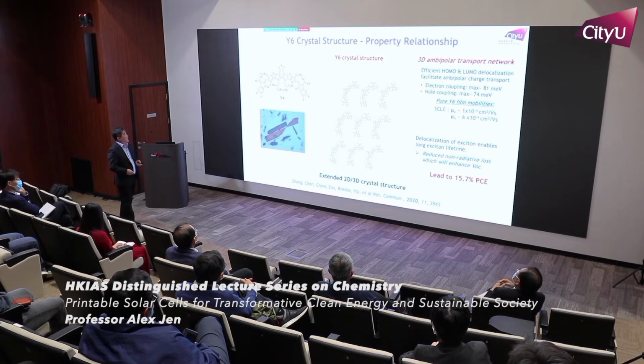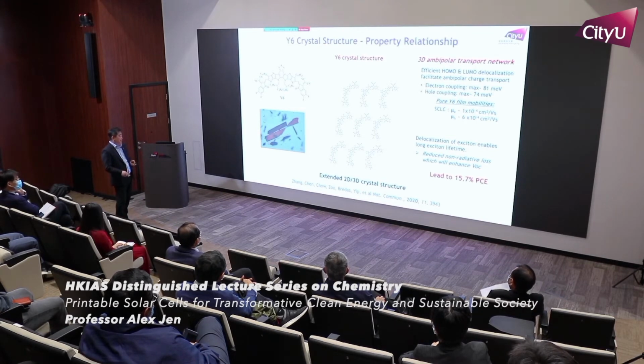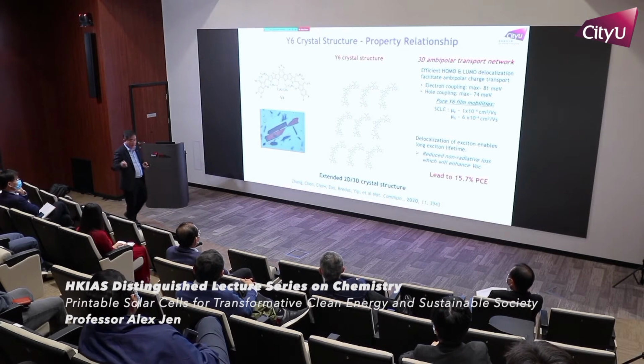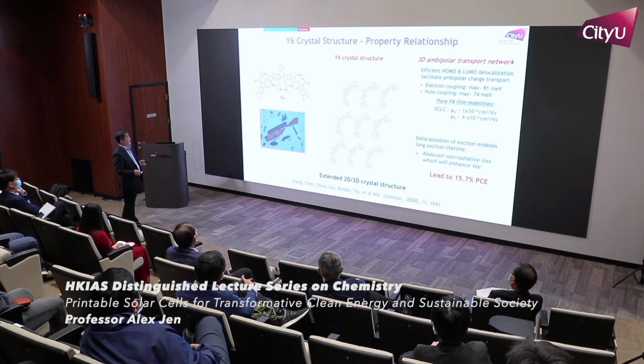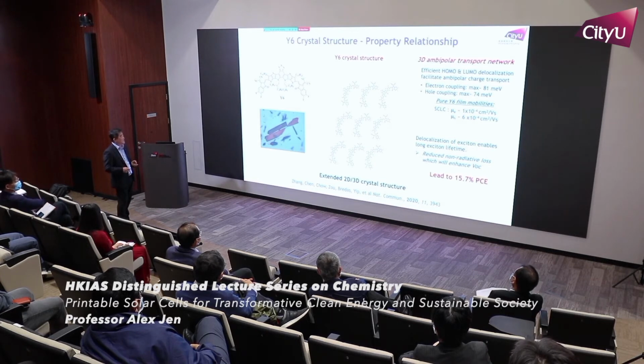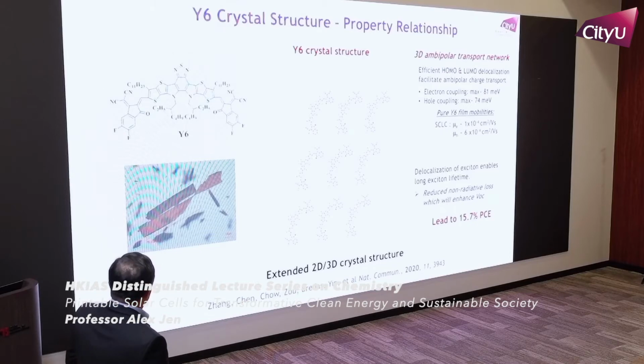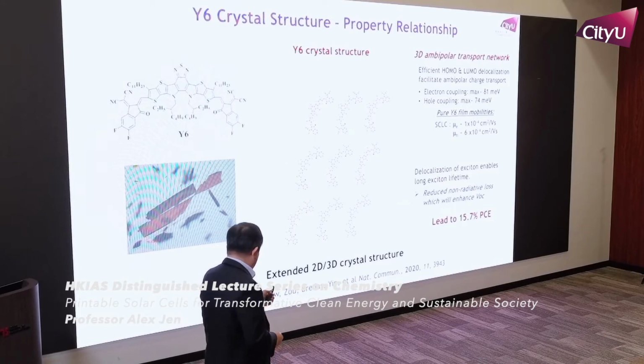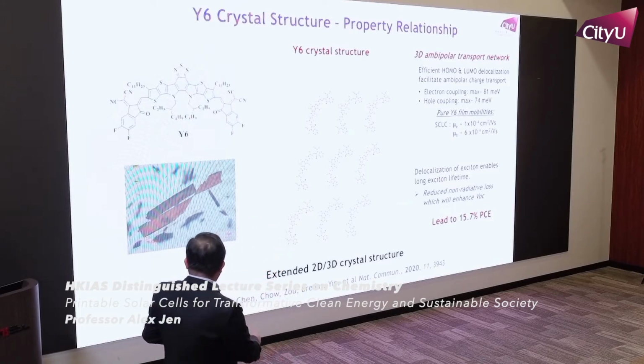And this is a work pioneered by Zhou Yinping, making this Y6 material, and then working with our colleague Angus Ip to study the reason why this type of molecule, this non-fullerene acceptor, is very efficient. And if you can recall, this is exactly a similar type of pseudo-2D structure, but instead of ADA, this is ADADA, so a little bit more sophisticated. As a result, you can see they can form very nice single crystals out of this, a relatively large single crystal.